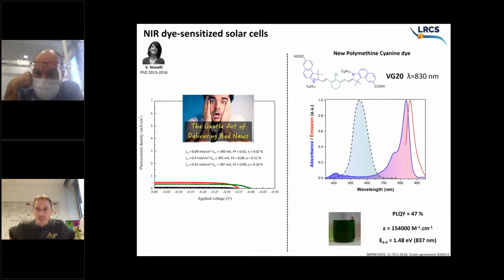This is a polymethine cyanine dye. So cyanine dyes are very interesting as molecules that are very luminescent in the near infrared. So this is the structure of what we call the VG20. It absorbs at 830 nanometers. And this here is the UV-vis absorption spectrum of the dye in solution. This is the emission, a very sharp emission, also in the near infrared part, and this is the photopic response of the retina, of human eyes.